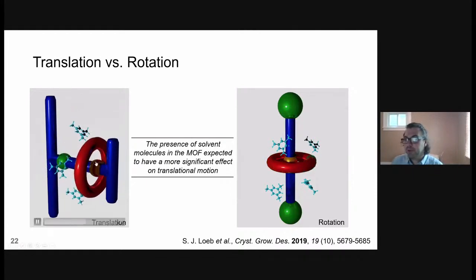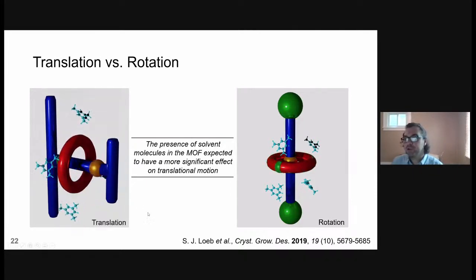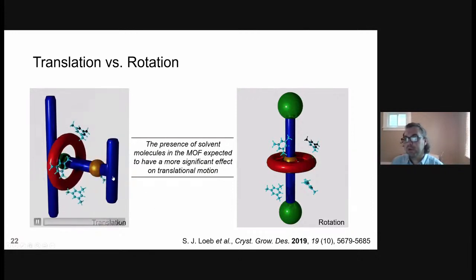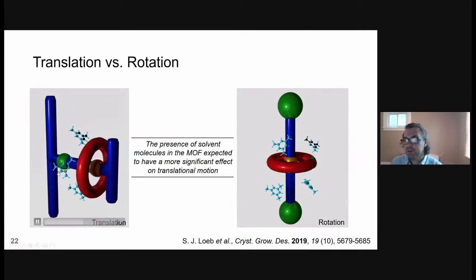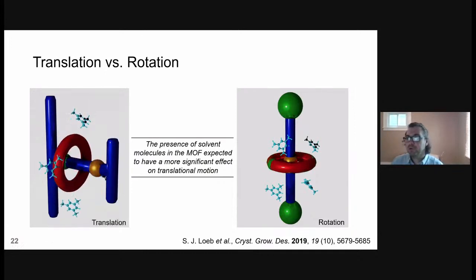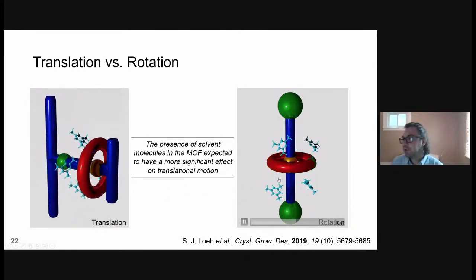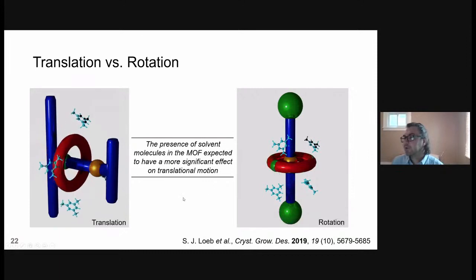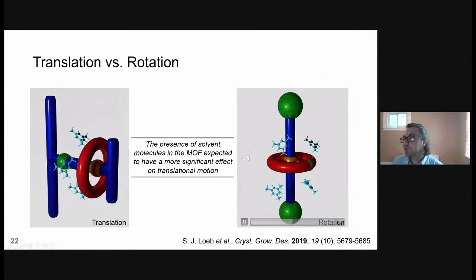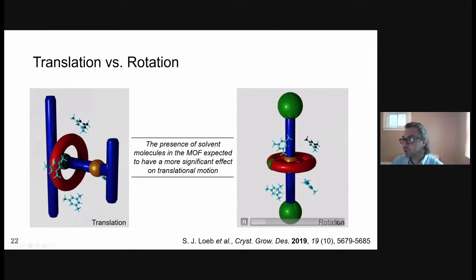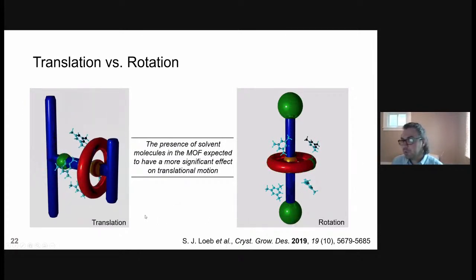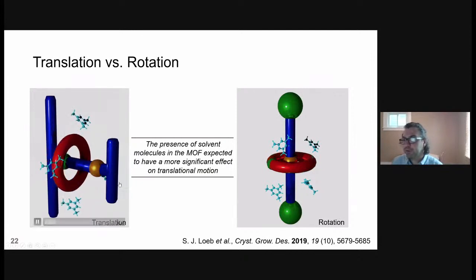For example, if we think about this translational motion, which I covered in this presentation, the volume occupied by the ring changes as it moves from one recognition site to the other, which when we have a solvent-loaded pore is going to result in reordering of the solvent. However, if we think about rotation, where the volume occupied by the ring doesn't change significantly during its rotational motion, this is going to result in effectively negligible reordering of the solvent. So potentially the nature of the solvent or the presence of it is going to have a much smaller effect than in systems where we're looking at translation.